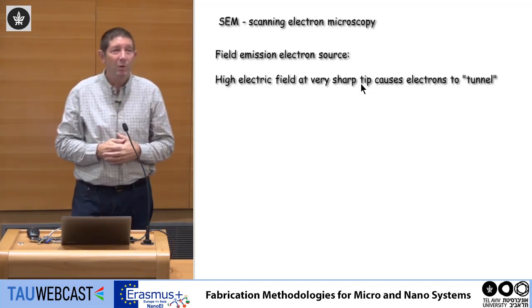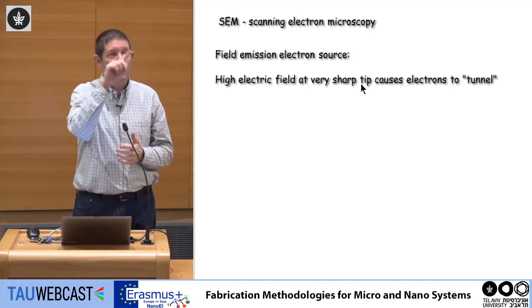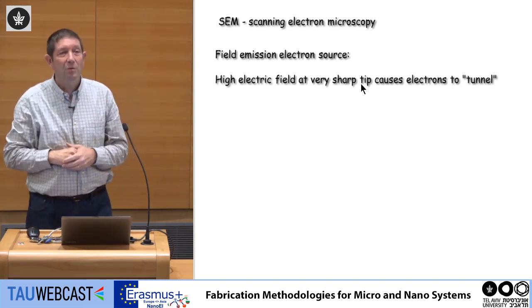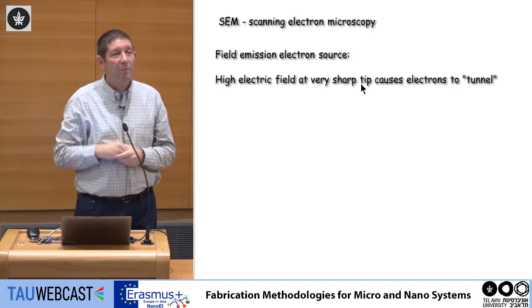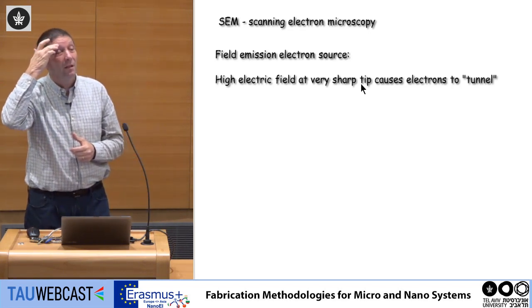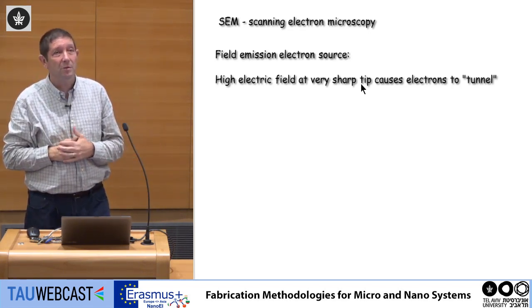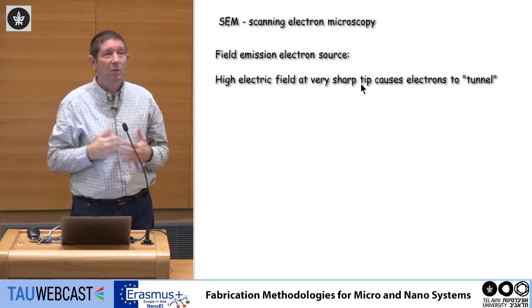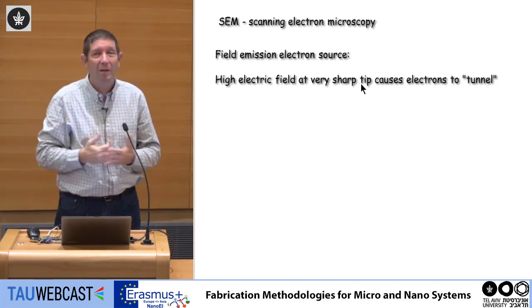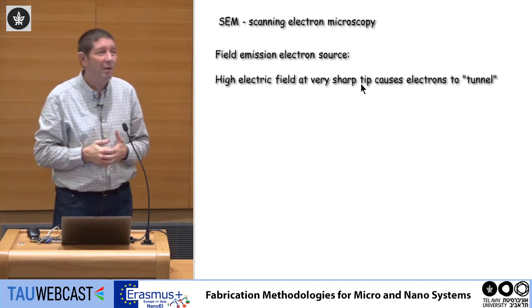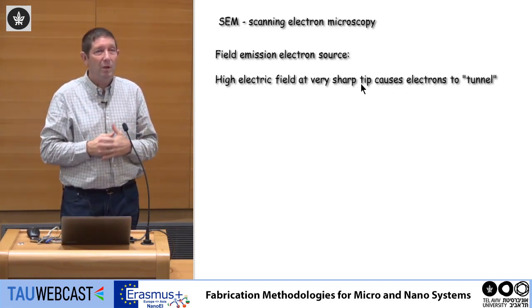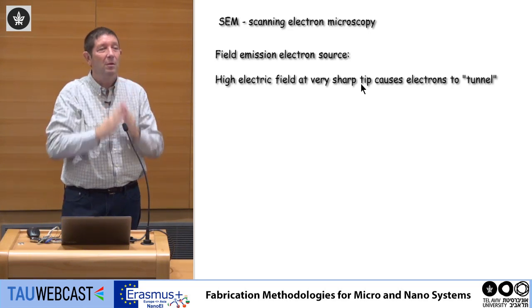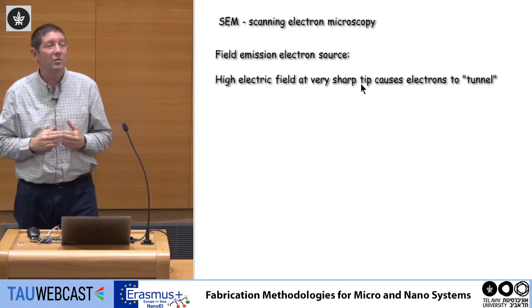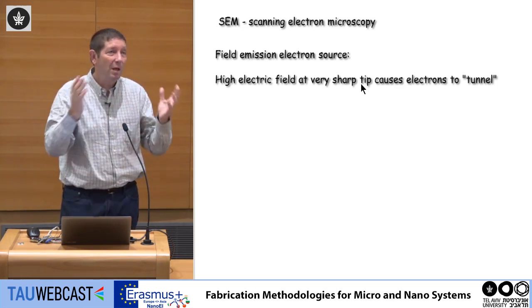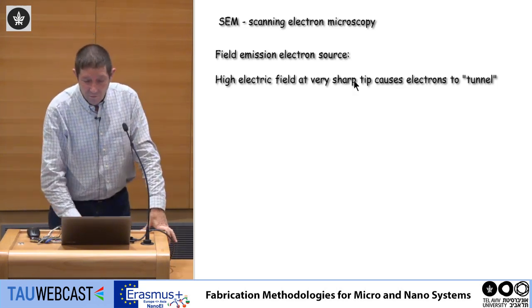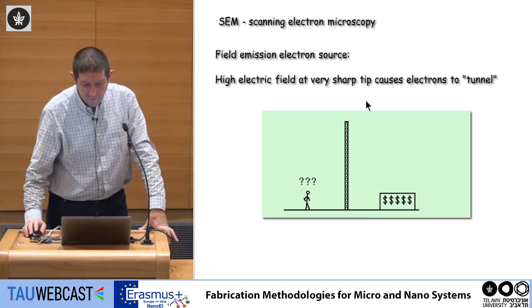But if you put like 10 volts, and the radius of curvature of your tip is 10 to the minus 6 centimeter, and 10 to the minus 6 centimeter is 10 nanometers. Now, when you work today with a high resolution technology, 10 nanometers is not so small. So if you can tune your tip to be in the range of 10 to the minus 6 centimeter, and you put 10 volts on the tip, you can have field emission. So the electrons can tunnel through.